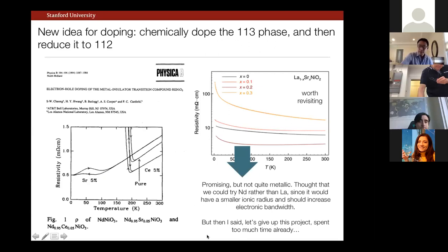So with that kind of fragile link, we continued this work, and the idea for doping was perhaps rather than trying to dope the infinite layer compound after synthesis, why don't we chemically dope the perovskite phase and then reduce it to the infinite layer phase?